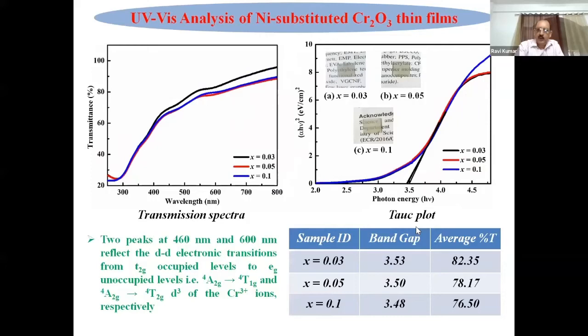Then come to the nickel case. Again, the transparency is good, 70 to 80% or higher than that in the visible range. And the band gap is 3.53, 3.50, 3.48, above 3 electron volt. So that is the beauty of this experiment. It means these films are transparent.